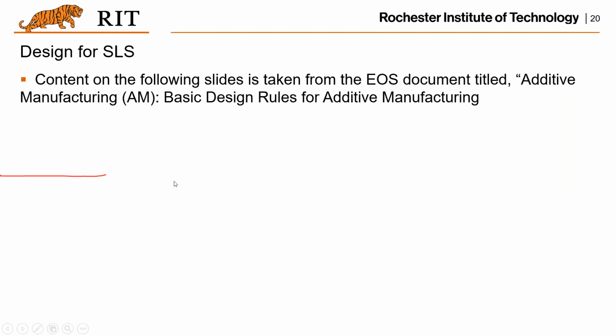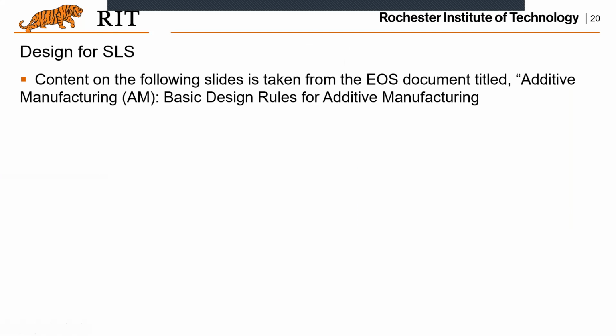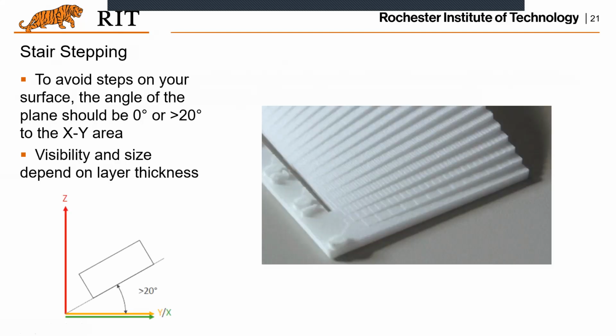So let's look at the design principles for such a process. Basically, these design guidelines or principles are related to a certain process. The first principle is the angles of the plane. In order to avoid the step effect, the angle of the plane should be either 0 degrees or larger than 20 degrees to the XY plane. And basically, if you look at this, that tells how you measure these angles.